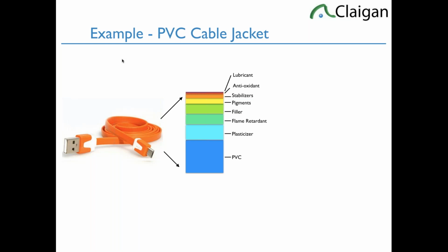They'll often have a very small concentration of antioxidants. So when the PVC is extruded into the cable form, it doesn't react with the oxygen and create a burnt effect. The burnt effect not only changes color, but it changes the physical properties. As it oxidizes or physically has a burnt effect with the oxygen in the atmosphere, it will change the color and degrade the plastic. And so often it needs an antioxidant to prevent that from occurring.